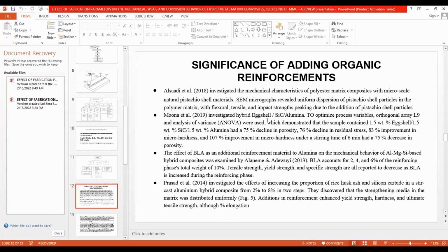Some hybrid composites are also made by using egg shell in collaboration with silicon carbide as well as alumina. You have some good results: a decline in porosity up to 75%, a 76% decline in the residual stress, 83% improvement in the micro hardness, and 107% improvement in the micro hardness under a stirring time of 6 minutes has been achieved.